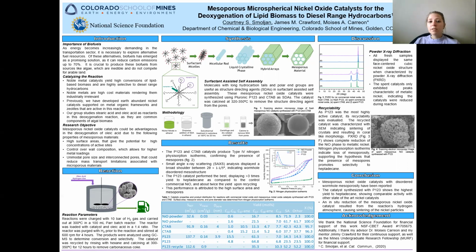These were synthesized using surfactant-assisted self-assembly. The surfactants that we used were Pluronic P123 and CTAB. These are just long molecules that basically determine the size of the pore of the material.